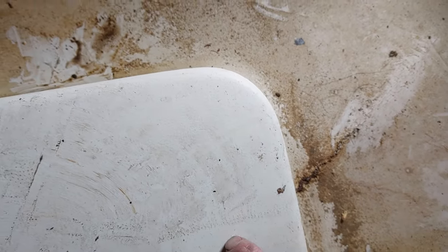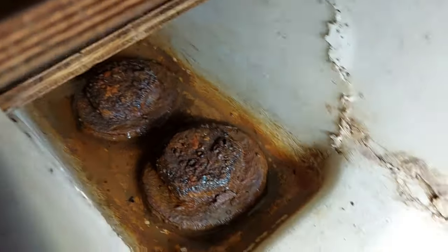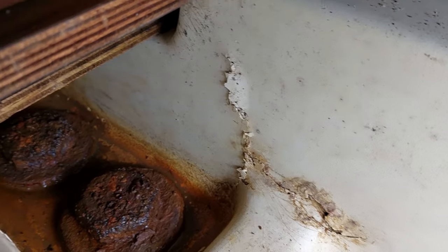Here we've got the frame that is actually pushed. This area is just a pan flash moulding, but these areas here are literally torn right across. There's more of the structure over here that's fractured — probably not so easy to see, but you can see that's quite a deep fracture going in there. Going forward one frame, again completely fractured across.